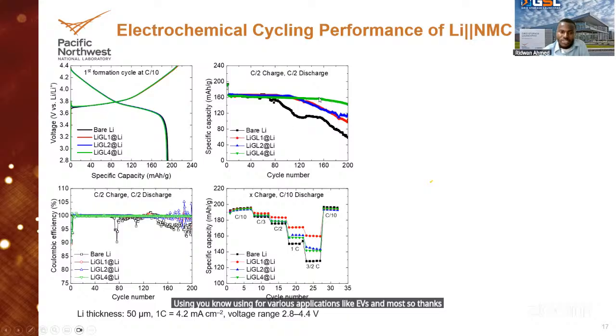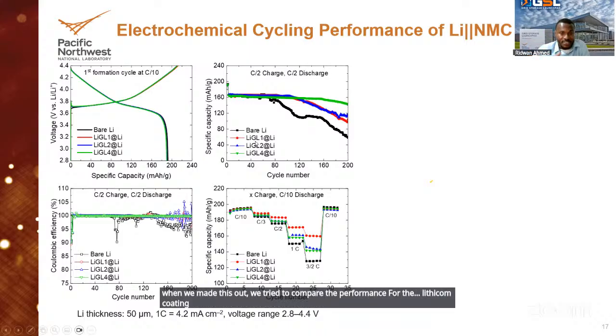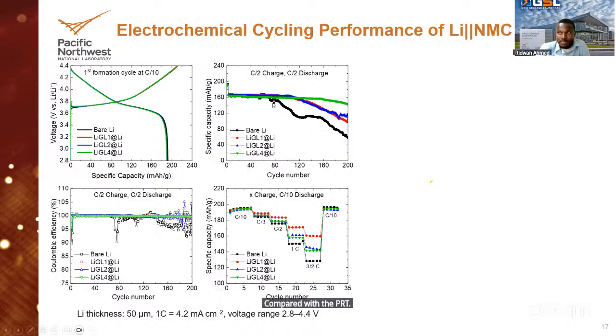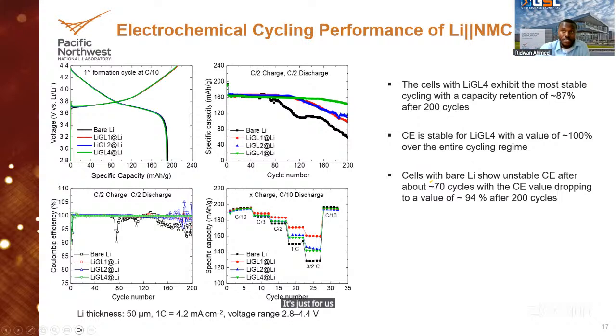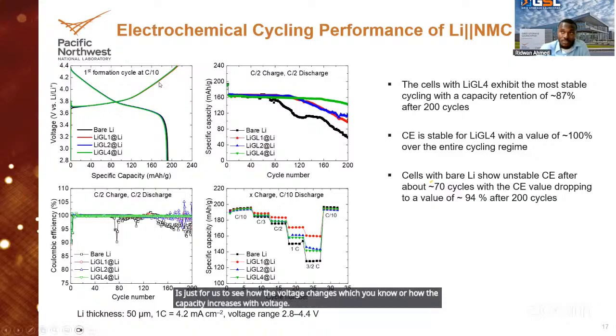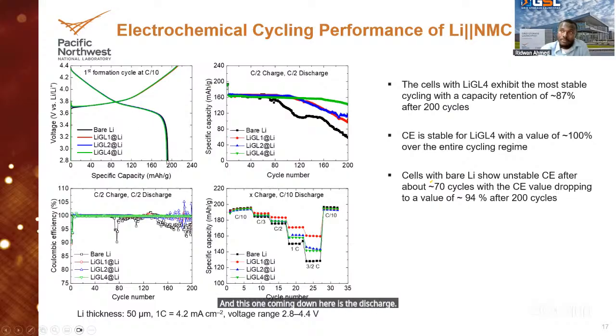When we made these cells, we tried to compare performance for the lithium coatings at different thicknesses. We compare with the bare lithium, which is the black line here. Again, the first graph here, I think I didn't explain it in the previous slide. This is what we call the voltage profile. It's just for us to see how the voltage changes with capacity. This is charge, the capacity as you charge the cell, and this one coming down here is the discharge profile for the cells. Again, this can give you a lot of information about batteries, but that's not the main focus of this discussion.